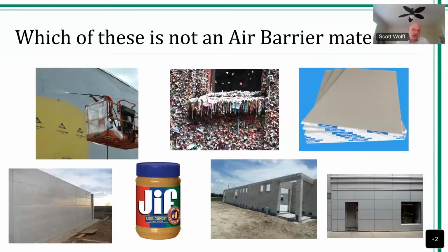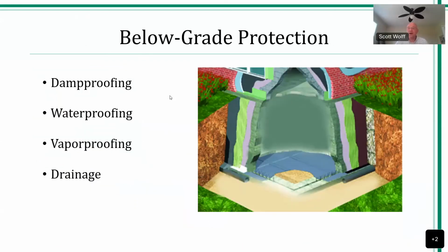So this is the kitschy slide we have here. Which of these is not an air barrier material? The reality is that all of these materials are qualified as an air barrier. Even Jif peanut butter. If anybody's familiar with the Air Barrier Association of America, Laverne Daglish, who is the principal there, actually did an air leakage test based on that referenced E2178 standard, and found that yes, in fact, it did not allow any more air leakage than dictated by that standard. Cast in place concrete, core filled or grouted CMU, are all an air barrier. Same with gypsum panel products. Even plywood and OSB are qualified as air barriers, but they don't have the elongation or the tensile properties of the membranes that we were talking about.